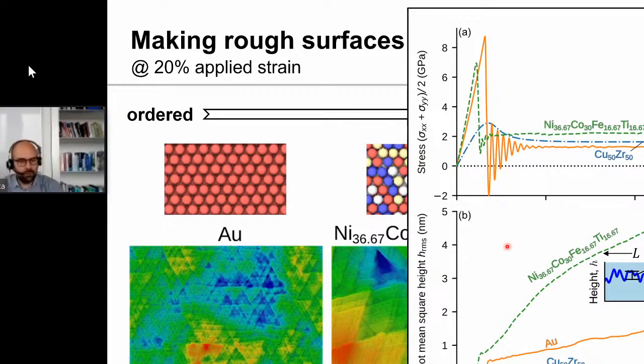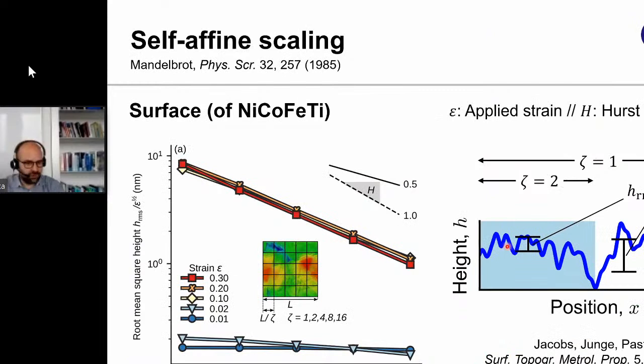Now we can look in a little more detail. We can again come back to this question of self-affinity. We haven't looked at the power spectrum. We have used a little more direct measure of self-affinity that goes back to what Mandelbrot did a couple of decades ago. We look again at the amplitude of height fluctuation, this HRMS, as a function of scale or length. If the scale is equal to 1, we are measuring HRMS over the full size of the system, for one half only over half of this, and so on. So essentially, we are measuring HRMS in these little squares and varying the size of the squares of this grid that I've plotted on the surface in the left plot here.